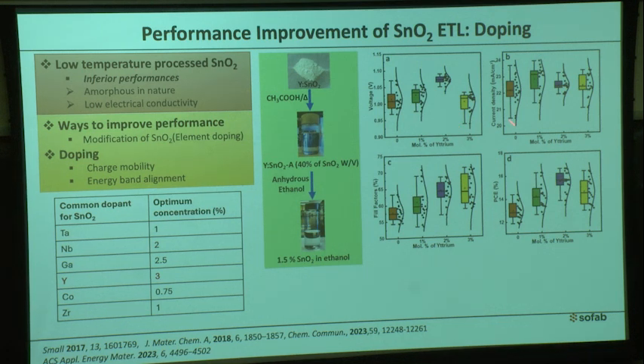This is the box plot which summarizes the power conversion performance of the flexible solar cells fabricated by depositing yttrium doped tin oxide directly on top of the perovskite. If you look here, we got higher power conversion efficiency from the tin oxide which contains 2% yttrium.